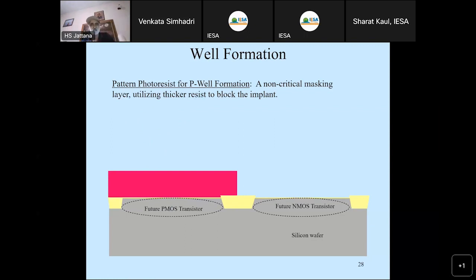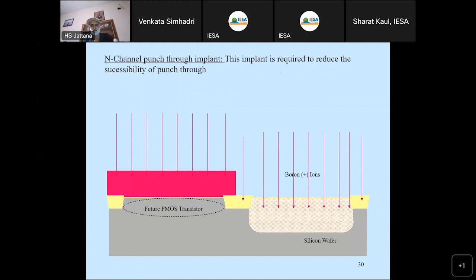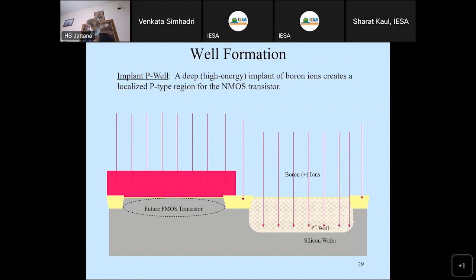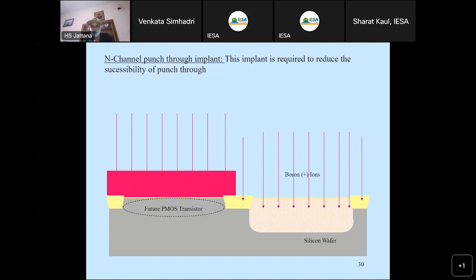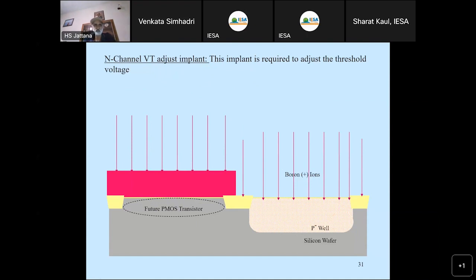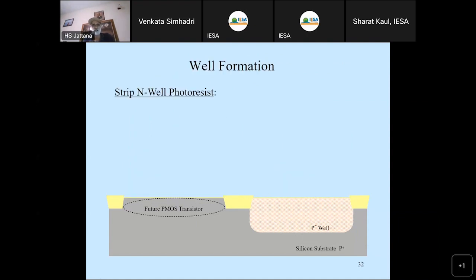And I will select, like here, what I am doing is I am putting photoresist for P well formation, because where the NMOS transistor is there, a P well has to be formed, and this area in the red I am blocking by a photoresist, and I will do the well engineering here. As you can see the steps, a number of implants will come. First, the high energy implant will come, and here, as you can see in the red, it will not penetrate inside this area, but here it is there. And then other implants will come, the punch through implant, then the VT adjustment implant will come. So all those implants will come. And then finally I will strip this. The P well is formed.